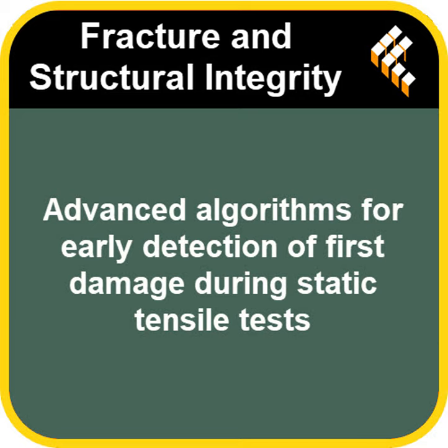Oh, absolutely. There's always room for improvement. While the bilinear model, the two straight lines, is great for spotting that first inflection point, it's still a simplification. It's not really designed to perfectly model the entire temperature curve, especially in phase 2, where the heat generated from damage can make the temperature rise nonlinearly. So maybe more complex mathematical models could give an even richer picture of what's happening after the initial damage starts. Potentially, yes. That's one avenue.